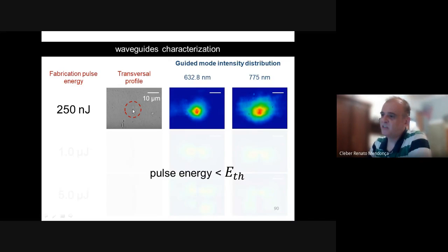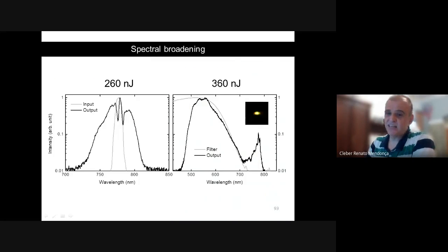Here are some other pictures. So here's the waveguide again, and of course we can actually see the modes of the waveguides, of light being guided at different wavelengths. Because it's a tough glass, we can also do something nicer, which is, instead of just coupling a very weak laser, we can couple a femtosecond laser in this Gorilla Glass waveguide, and then in this case we can get an effect which is similar to the white light continuum generation that I mentioned before.